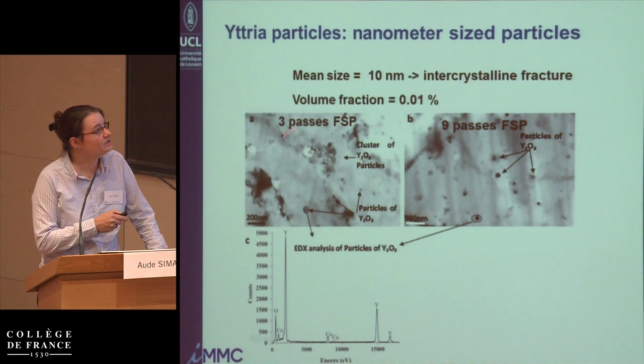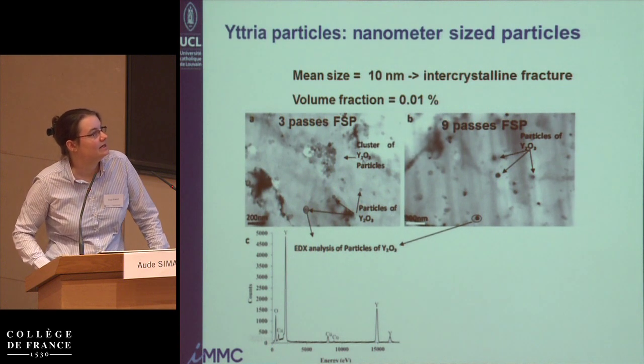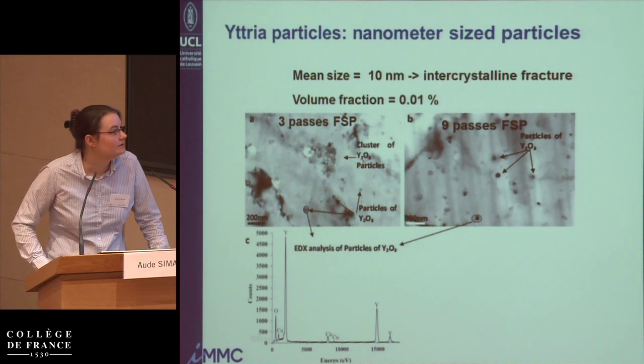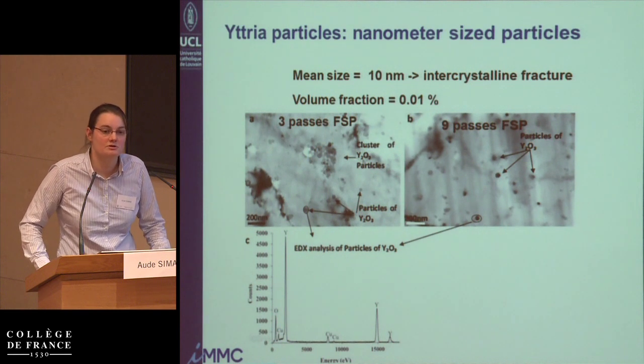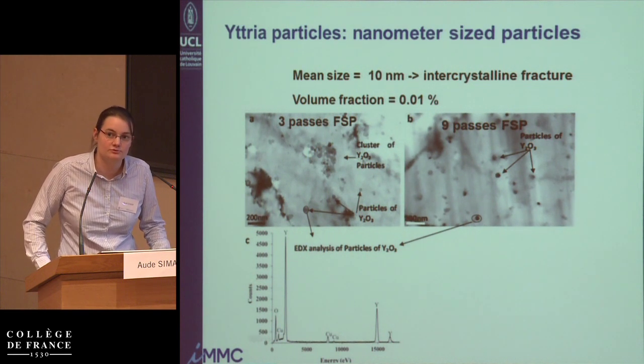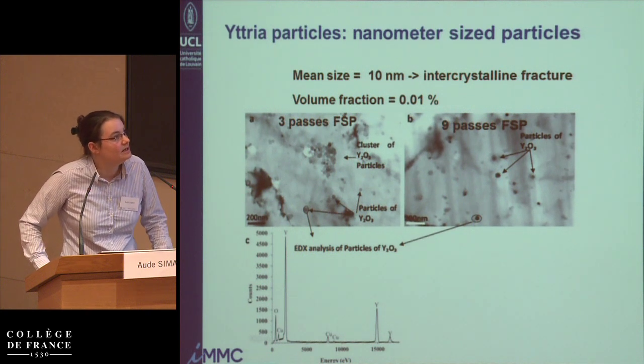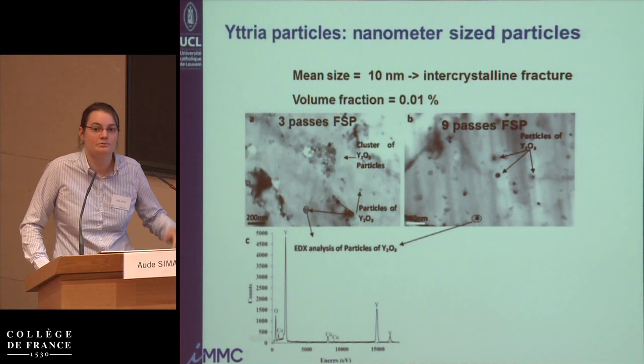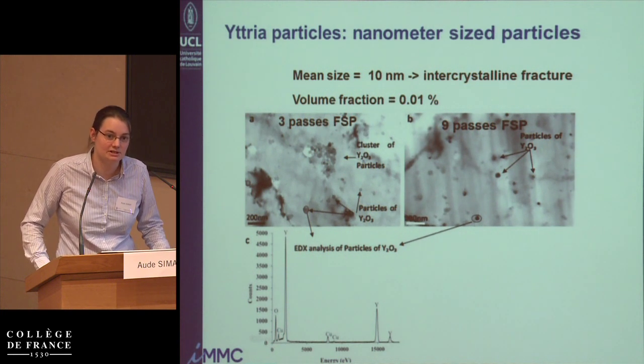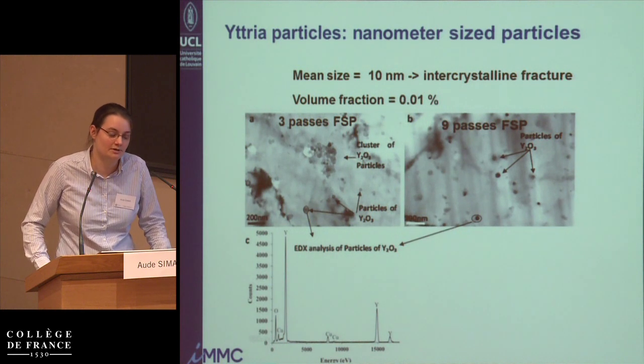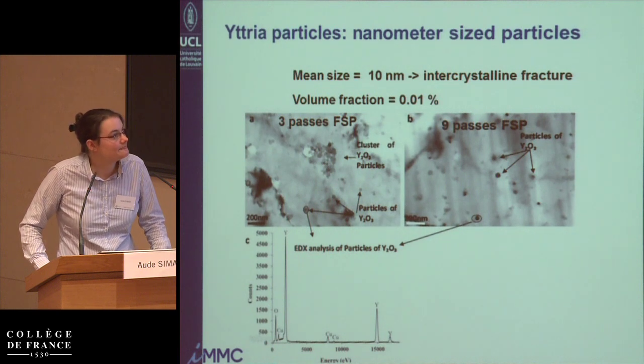Now, you see that after 3 passes, we had still some clustering remaining, and the composite is not sufficiently homogeneous to the level that we were expecting. Now, after 9 passes, what we have been able to see, but of course in the transmission electron microscope you see a very small region, it looks like it's much more homogeneous. So that goes well with our observation at a larger scale.